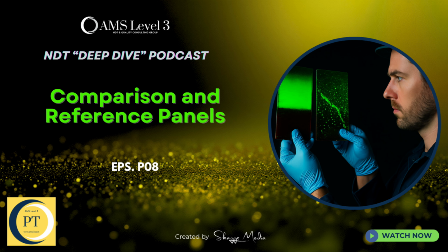The panel usually has steps, maybe 6, with cracks going from very fine to coarser. And the main goal here is generating these brightness contrast curves, like the H&D curves from old school photography. What do those curves tell you? They quantify really critical things. First, the slope or steepness of the curve, called gamma, measures brightness contrast. Basically, how the system distinguishes between different levels of penetrant, which relates to sensitivity.